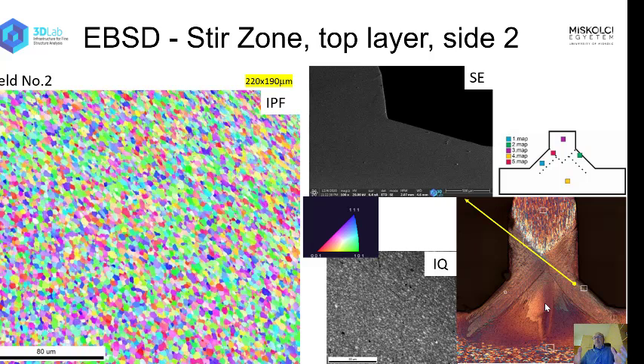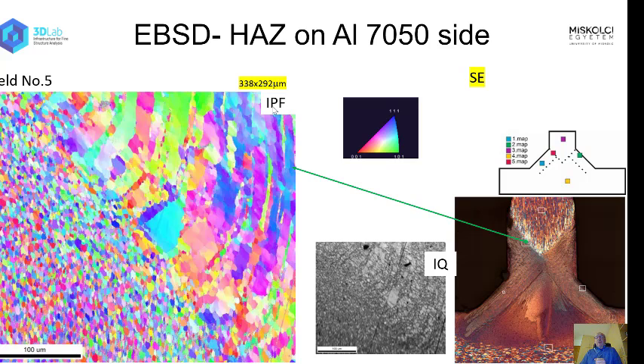So basically, we looked at the Barker's, and then we looked at a very, very small scale. So we're talking about orders of magnitude smaller. Here we're looking at the micron range. Here we're talking about millimeters. Yet one interesting correlation was that the EBSD in the coarse grain heat affected zone, and you can see the stir zone and the material, looks very, very similar to the color etchant. You can see the image quality indicator, which shows you how few precipitates and how few dislocations you have in those grains. Excellent pictures.